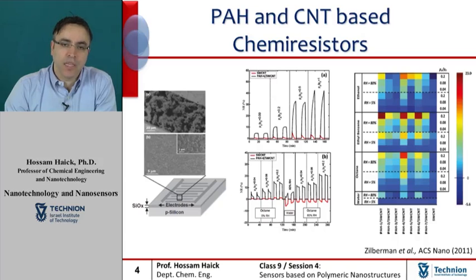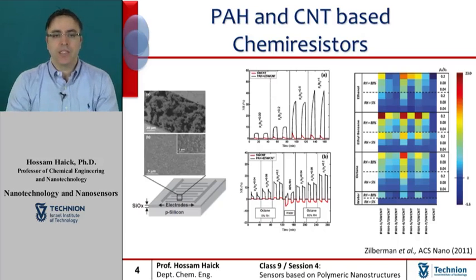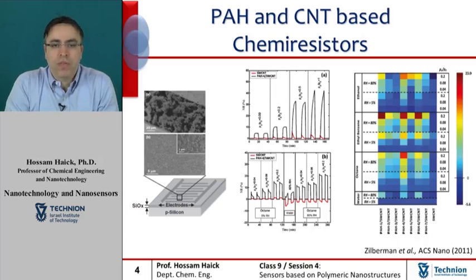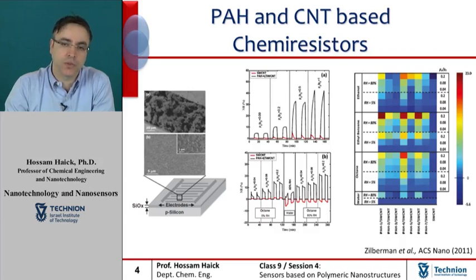In the right figure that is presented on the screen, you can see an image plot of the sensitivity values calculated from the pristine single-wall carbon nanotubes and the PAH single-wall carbon nanotube bilayers upon exposure to various volatile organic compounds at different concentrations and background humidity. As seen in the figure, each point in these plots is an average of 3 independent exposures from 3 duplicated sensors.